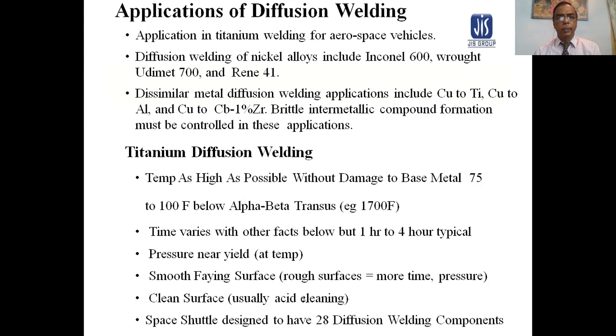Application of diffusion welding. Application in titanium welding for aerospace vehicles. Diffusion welding of nickel alloys includes Inconel 600, wrought Udimet 700, and Rene 41. Dissimilar metal diffusion welding applications include copper to titanium, copper to aluminum, copper to columbium 1% zirconium. Brittle intermetallic compound formation must be controlled in these applications.